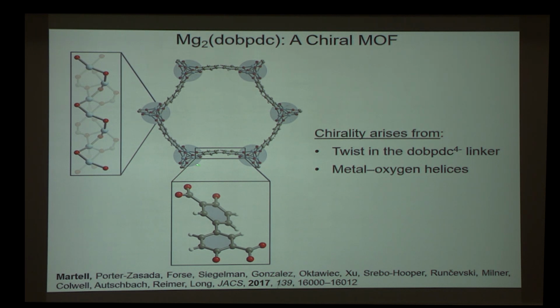Also, each corner of the hexagon-shaped channel is a metal oxygen helix. From this perspective, the helix is running into the screen, but here I've laid it out from bottom to top. So you can see if you trace the oxygens and the metal sites, it is a left-handed helix, and this is a chiral structure. In this structure I'm showing here, each corner is a left-handed helix. There are no right-handed helices.